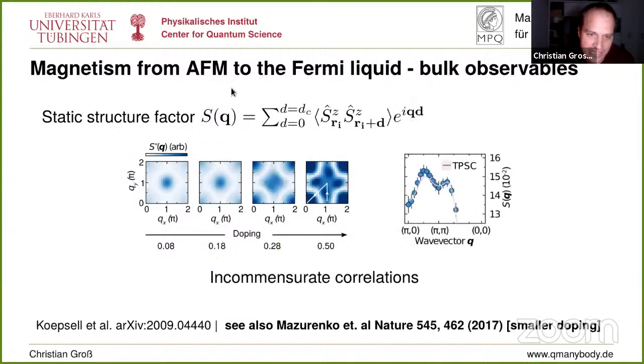And of course, we can also do that more quantitatively, basically moving through a path like this through the Brillouin zone. You see basically the data here, and we put actually this TPSC. This is one of these perturbation theories on it, and we see that makes really a nice match.